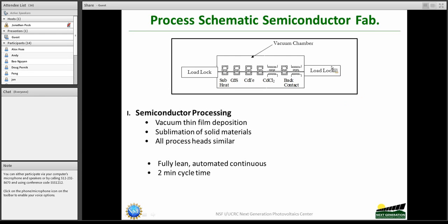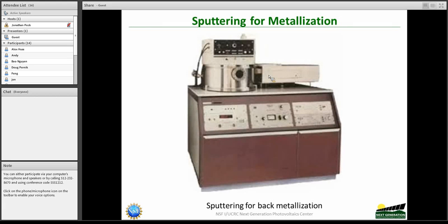So this completes the process of making the N layer, the P layer, the doping at the back, and improving the material by this cadmium chloride treatment, except for the back metallization. And the back metallization is done by a sputtering process, where here is a load lock. You come in and deposit the metal at the back for the sputtering process. So this essentially completes the manufacturing of a cadmium telluride solar cell.